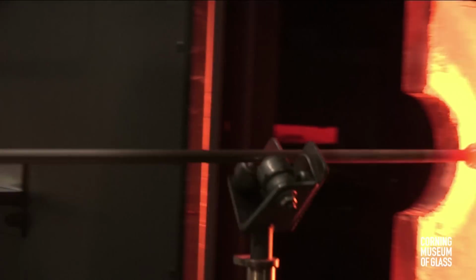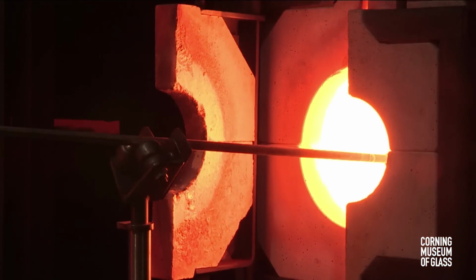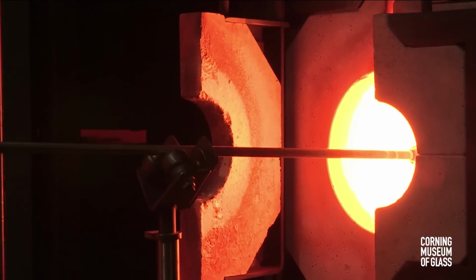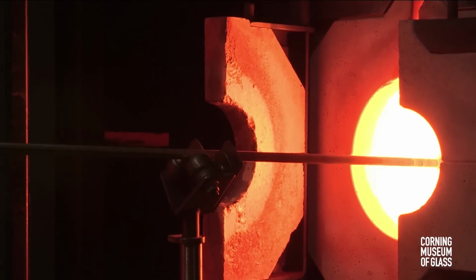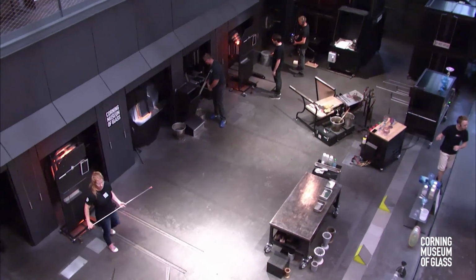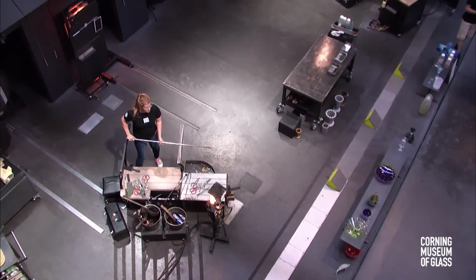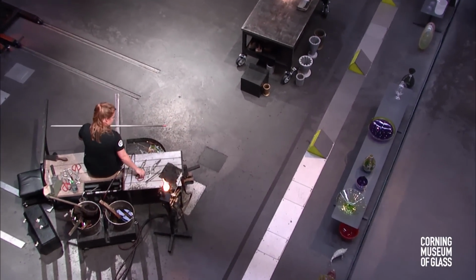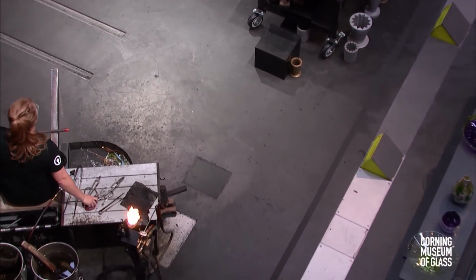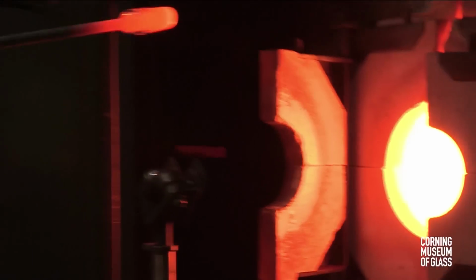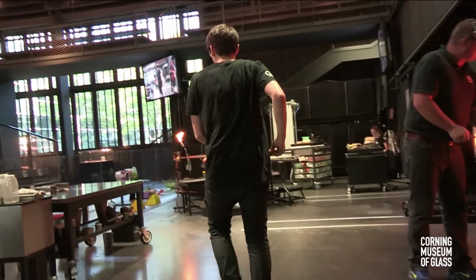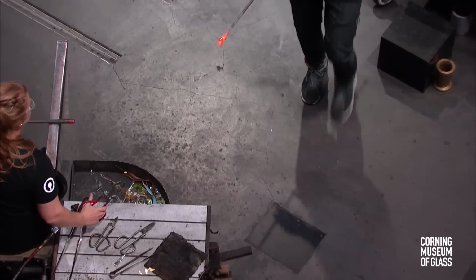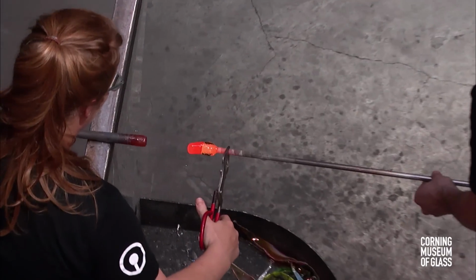Again, this soda lime glass is very prone to thermal shock. If it cools too quickly below 900, that's really the safe temperature line for this type of glass, it's going to crack, or it wants to crack. When we're done with this piece and everything that you see up here, we put them through a slow cooling process called annealing. And the annealing for this will take about 8 hours to slowly cool. And we'll talk more about that.